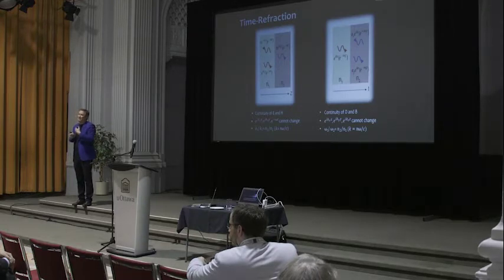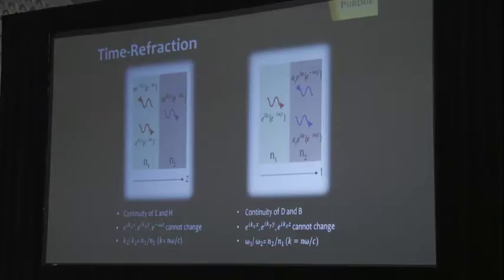So honestly, I think that's really important. Arguably, again, what is one of the most important devices? Spatial light modulator, but it's slow. Here, I could do it really fast. So it would be like a space and time light modulator. For that, we need the right materials. And I think TCOs could do the job, because the change in the refractive index is large, and the resulting change in frequency is large. And of course, it's proportional to the change.